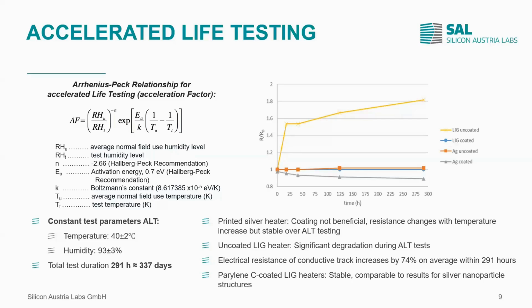You can see here that the uncoated silver heater even decreased its resistance. This might not be understandable, but if you think about what happened, this is a post-curing effect. What happens? Some residues of the solvents still evaporate. This can only happen in the case of the uncoated heater. In the case of the coated heater, it's encapsulated and nothing can evaporate anymore, so the resistance stays stable in this case.